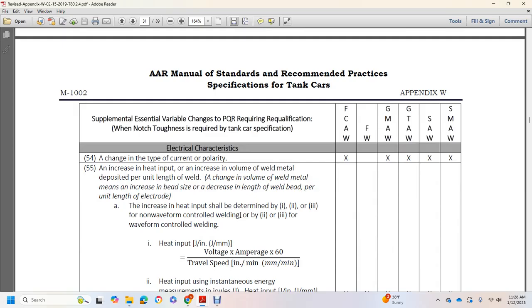55. An increase in the heat input, or an increase in the volume of weld metal deposited per unit length of weld. The change in the volume of the weld metal means an increase in the bead size or a decrease in the length of that weld bead per unit length of electrode.